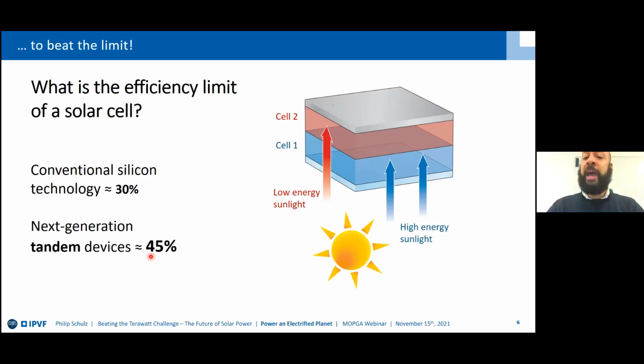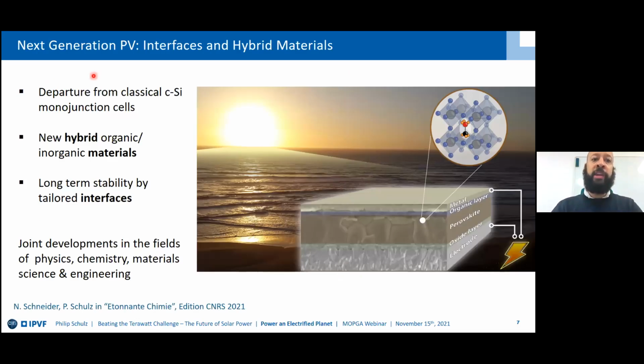Now, obviously, you cannot do this with exactly the same cells. The materials that absorb the sunlight need to have very specific capabilities and need to be made from different materials. And there is where these new hybrid materials that we're working on come into play. The new generation of photovoltaics really requires the perfection of the interfaces and also the inclusion of new materials. We depart from the classical crystalline silicon and use materials that are part inorganic, part organic, here in this Perovskite structure, and build them into these thin film devices.